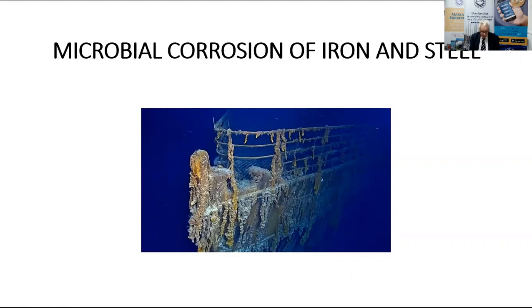The per diem corrosion rates were often as high as 800 milligrams per decimeter squared, or if it's easier to understand, pits several centimeters in diameter, 8 to 10 millimeters deep, were often found in 18 millimeter thick shipbuilding quality mild steel plate in less than 2 years. That's fast, believe me.